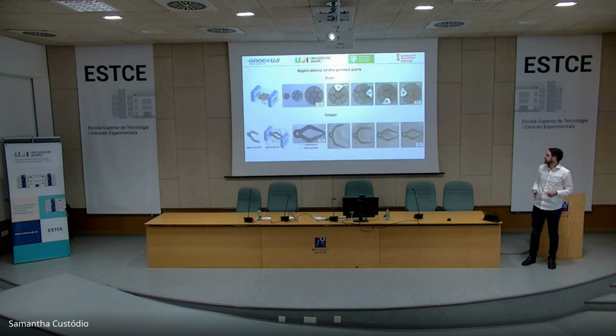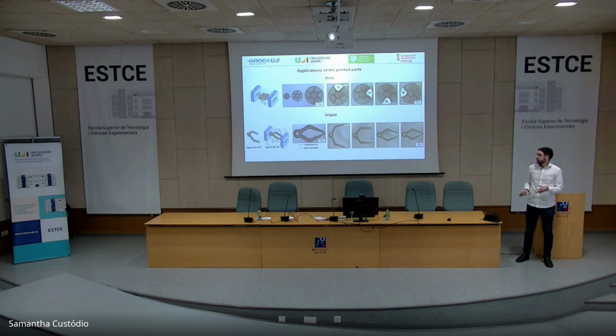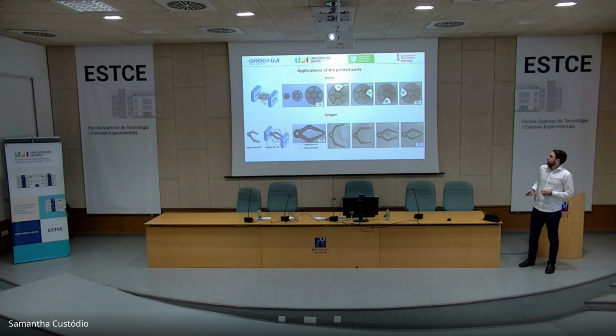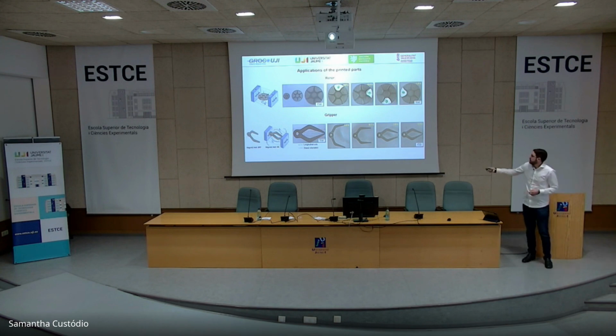And these strands are quite interesting because if we control the printing as we want, we can achieve different actuators. And that's quite interesting for robotics, for example. And the actuators that we tried, and with this I finish, were some rotors, which are basically controlled by an external magnetic field. We can control the rotation of these micro or millimeter scale structures that we were printing, and also some grippers. So we can control the opening and closing of the gripper just by an external magnetic field.